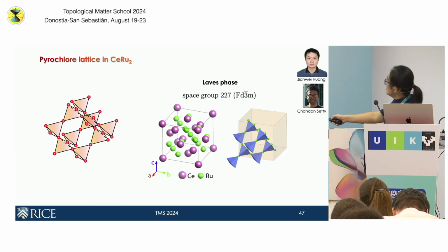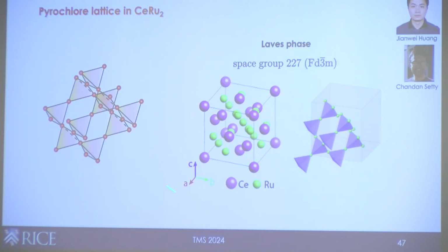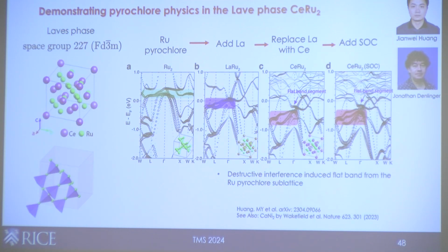How do you see that? So cerium ruthenium-2 looks like this, the crystal structure. The ruthenium sublattice forms the pyrochlore right here. So this is what it looks like. We started to measure this, and this is a cubic system. And along the way, we also got Jonathan Denlinger interested in looking at the band dispersions. So he did this whole series of calculations just to track what happens to the pyrochlore flat band as you add in the cerium. So this is a DFT calculation.